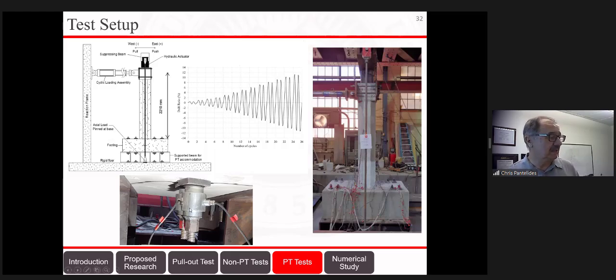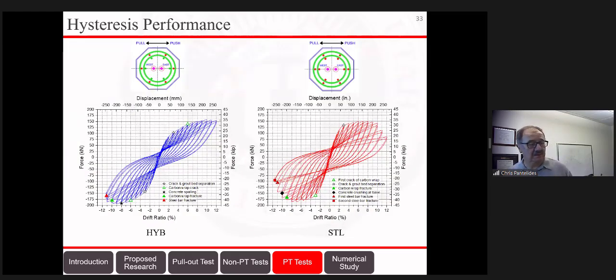And you can see here we kept an eye on the force level, the post-tensioning force in the bars, by these load cells. Each post-tensioning bar was initially post-tensioned to a force of 191 kilonewtons. So this force was deemed to be appropriate for this test, bearing in mind we could reach 10% drift ratio or higher.